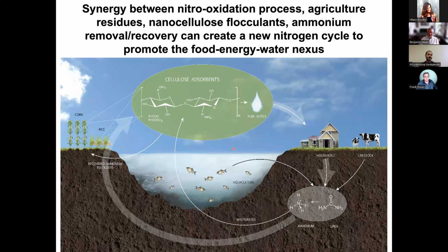And in our view, we can really use this nitro-oxidation process to have a circular design of taking the waste or residue from agriculture and modifying it, and then using it to remove excess amounts of ammonia or even nitrate. Nitrate is negatively charged, so we have to convert our system into positive charge, but that's not so difficult. And we do have a project using inorganic nanoparticles attached to the nanocellulose scaffold to remove nitrate.